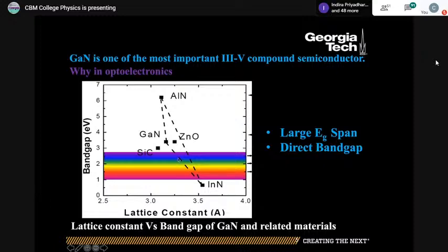to have light emission. Normally we have light emission of blue and green from indium gallium nitride materials. If we are forming a heterostructure, you can have indium gallium nitride as a quantum well and gallium nitride as a barrier, and you can form light emitting diode structures without any issues. So that's what we have done. I'm going to deal with it a little later.